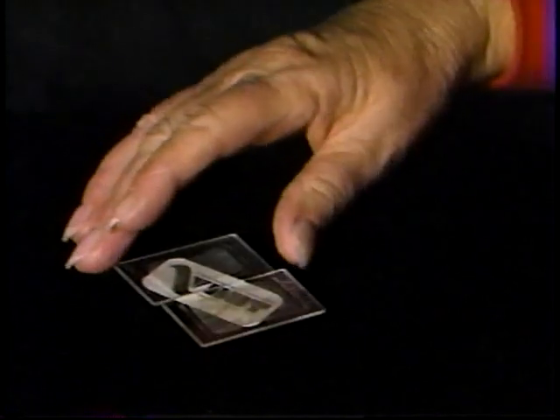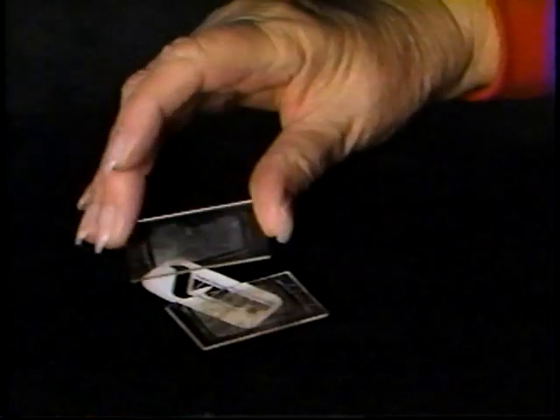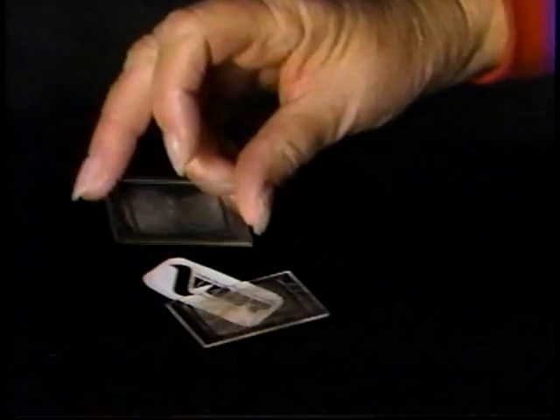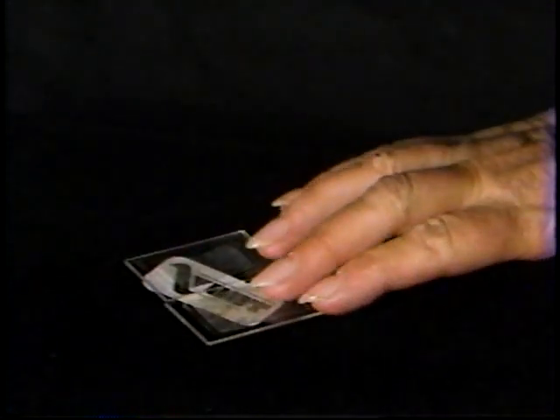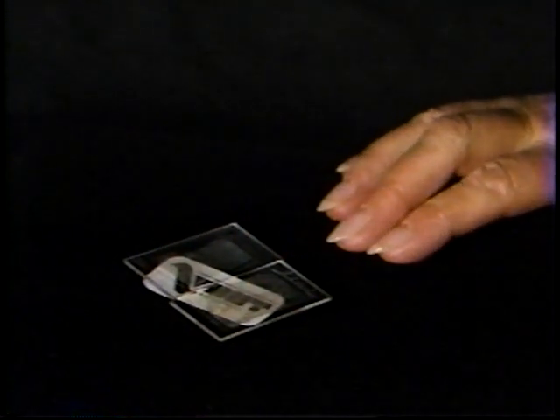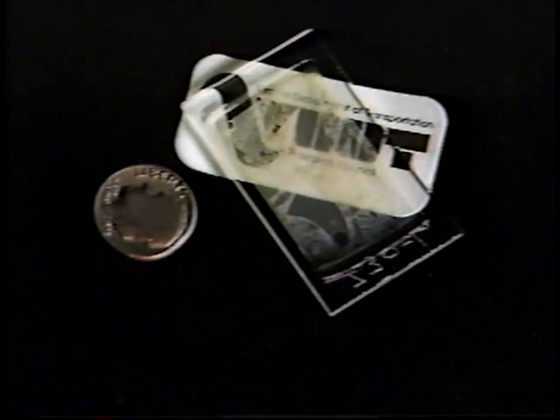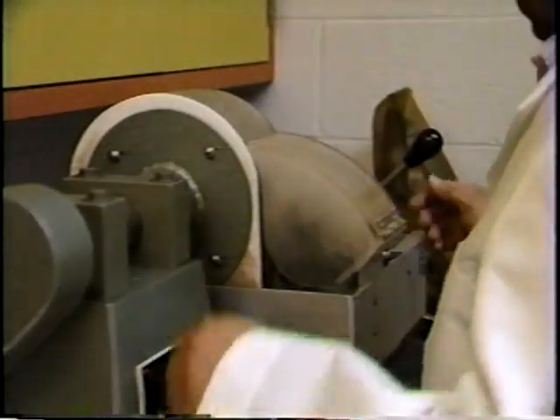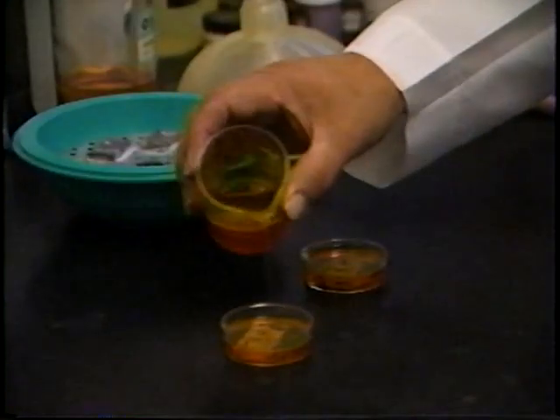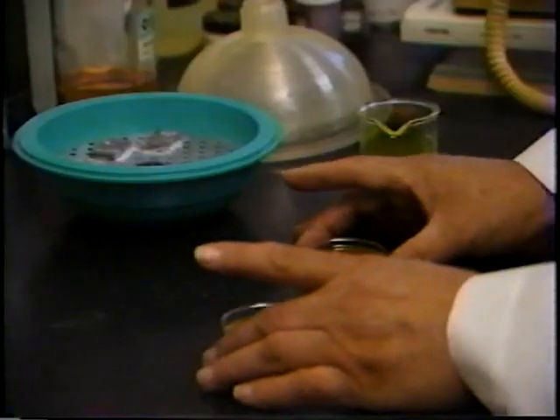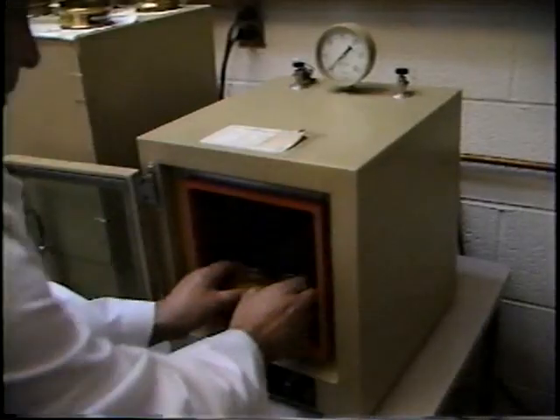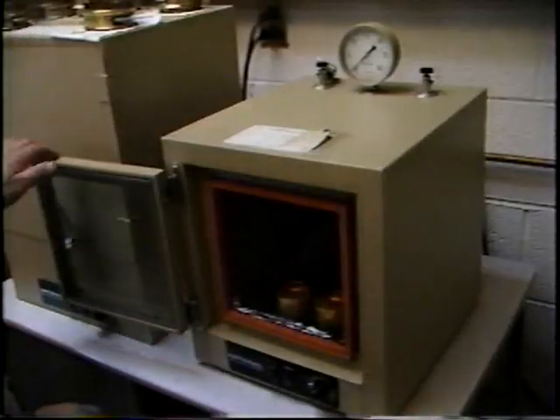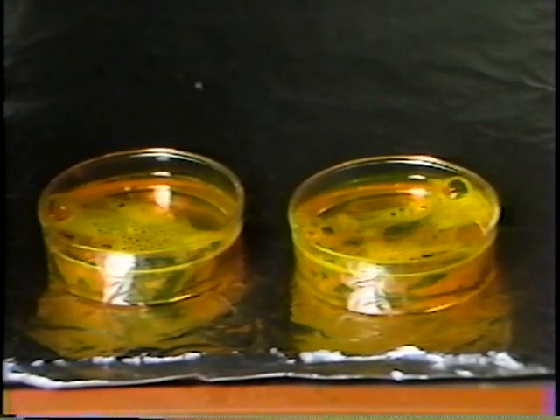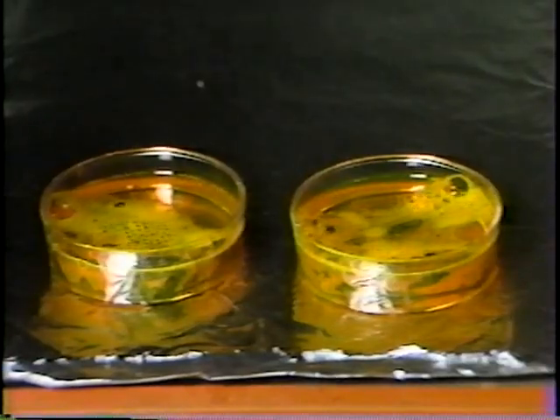In order to be viewed with this microscope, concrete must be sectioned, mounted on glass, and polished thin enough to read through. These specimens will be passed among you for you to examine. Naturally, the preparation of such super thin specimens requires special techniques and procedures. A smooth surface is produced by grinding, and then the specimen is covered with fluorescent dyed epoxy and vacuum impregnated in this vacuum oven. A low heat and 2 days' time is required to cure the specimens to a grindable texture.